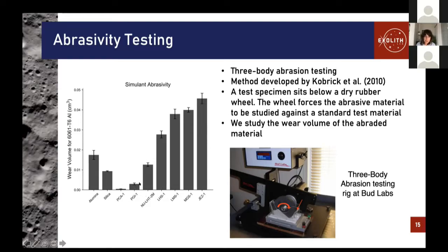So the least abrasive are these two simulants here, which are Phobos simulants that the Exolith lab created. And these are more of an asteroid composition with more clay material. So it's not surprising that they're less abrasive than, for example, LHS1 and LMS1, our two lunar simulants. They're much more abrasive. They wear away more of the aluminum.